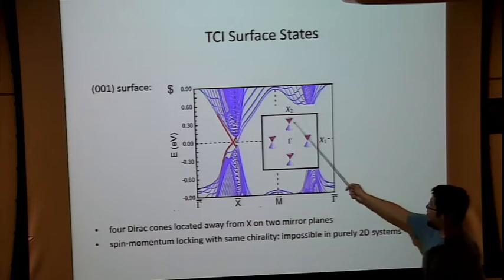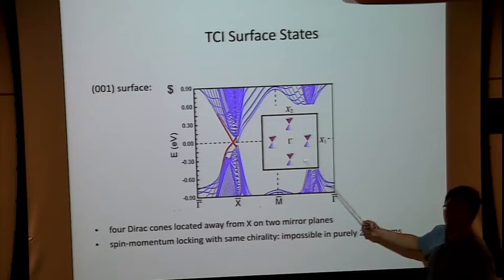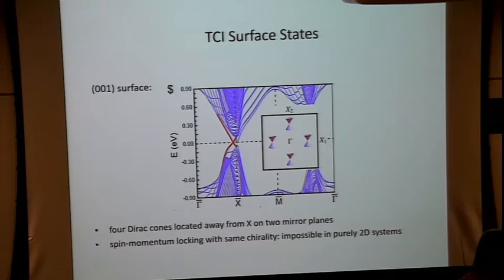So let me just continue that despite the presence of 4 Dirac cones, and despite that the position of the Dirac cone can change along these lines, so the Dirac cones can merge onto each other, still, even in that case, they cannot pair annihilate. So this is different from any two-dimensional material. For example, in pristine graphene, Dirac cones are located at the corner of the Brillouin zone, but if you stretch graphene in one direction, the Dirac points can move toward each other, and once they come to the same momentum point, they can pair annihilate. So here, these Dirac points can move, but they cannot pair annihilate. It's because of the topological index being non-zero. So this is what we call topological protection. So as long as mirror symmetry is present, they stay gapless.